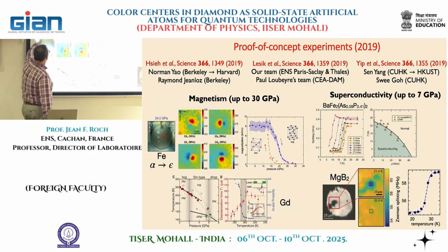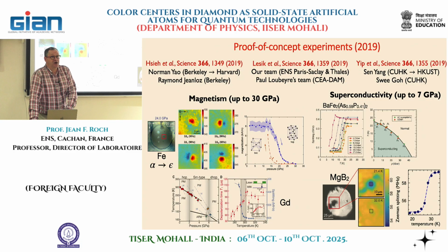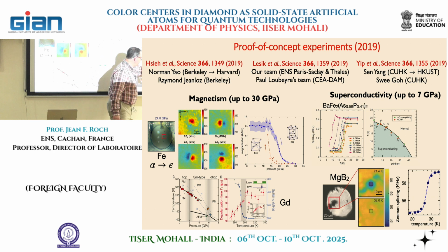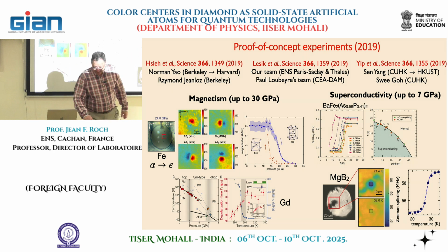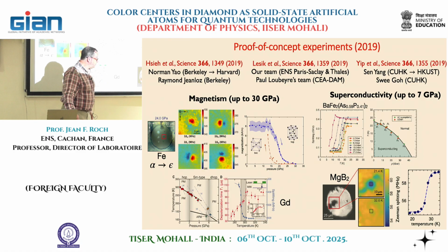And then another experiment we did, that are results that were obtained in Norm Yao's team on gadolinium. At the same time, we were looking at can we observe the superconductivity through the direct observation of the Meissner effect? And this is our proof of principle experiment. We put in the anvil here a system where we have now a powder of MgB2. MgB2 is a well-known superconductor, and its critical temperature will change with pressure.